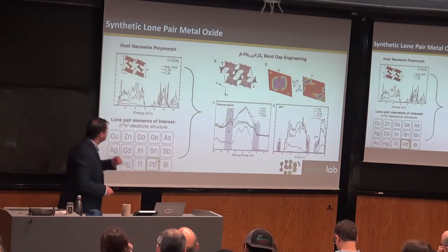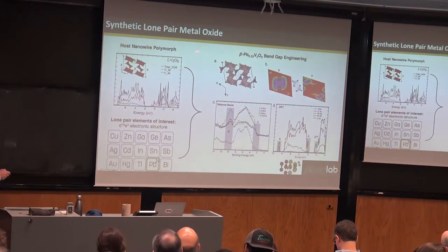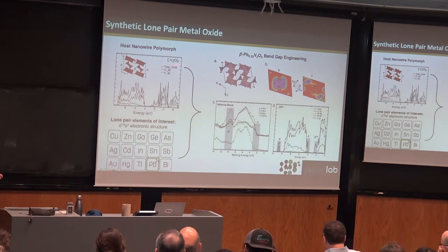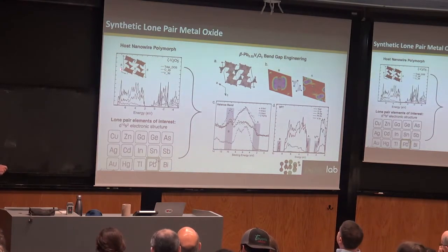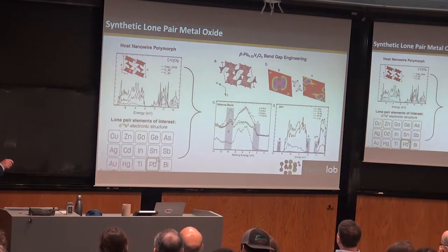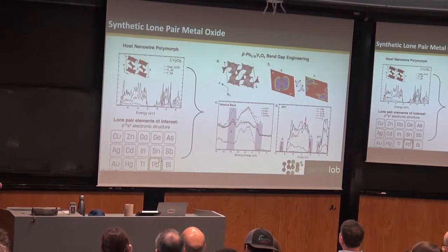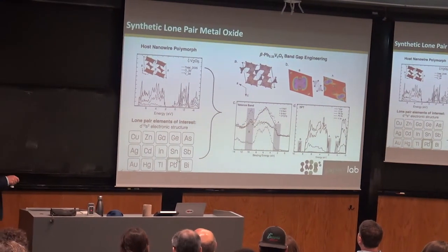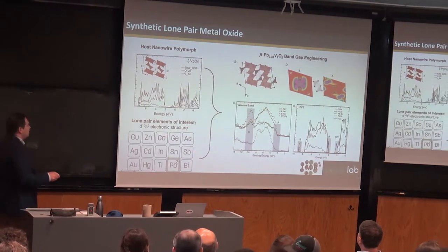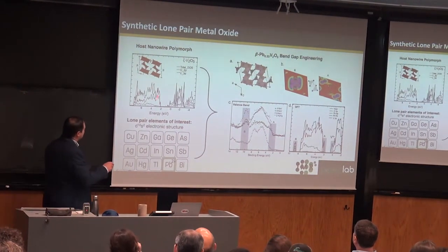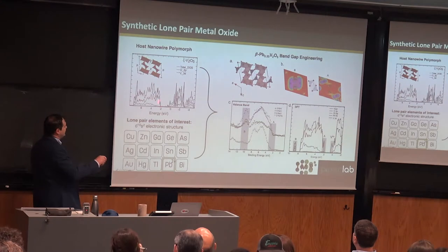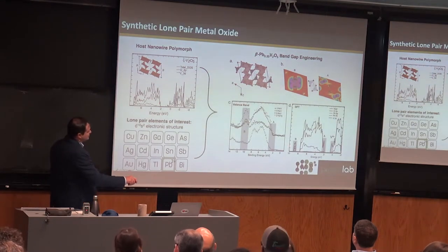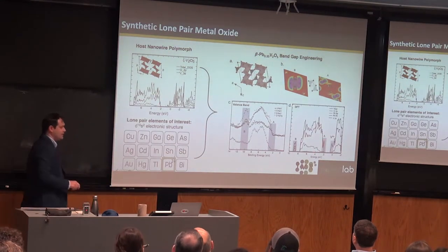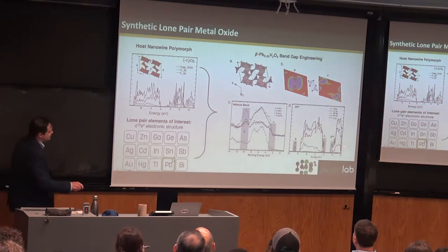So around that time, we took one of the V2O5 beta form, which is essentially one of these bronze-like structures without the bronze. These are sites where our ions can go, and so inserting lead 2 plus into this, confirming that we had the right character, what we found is we could change the electronic structure, so then we could introduce the bonding and anti-bonding states associated with the lone pair mechanism. This would raise our ionization potential.